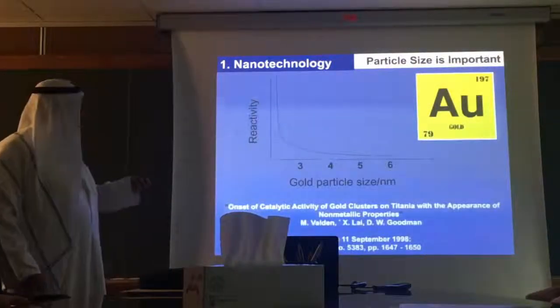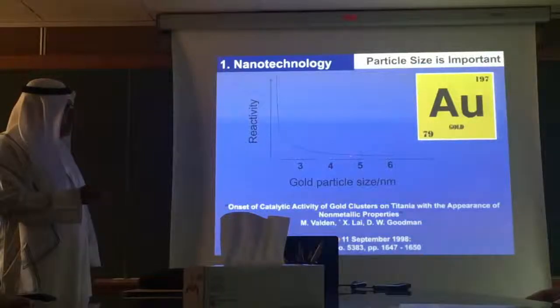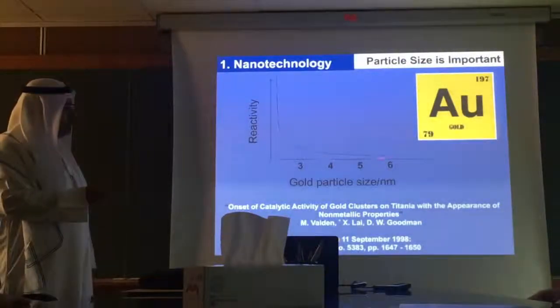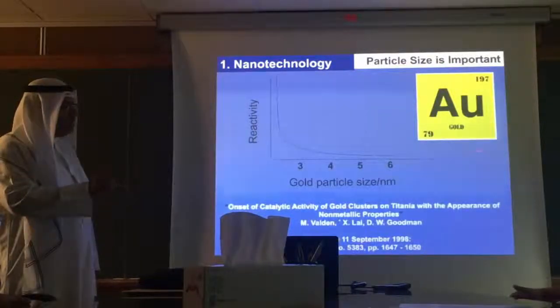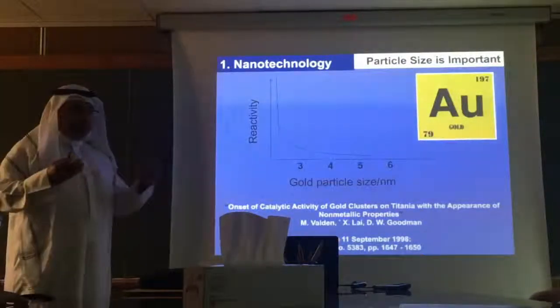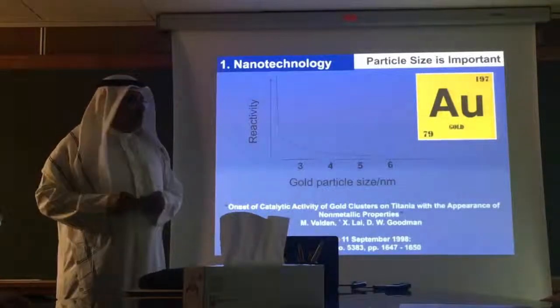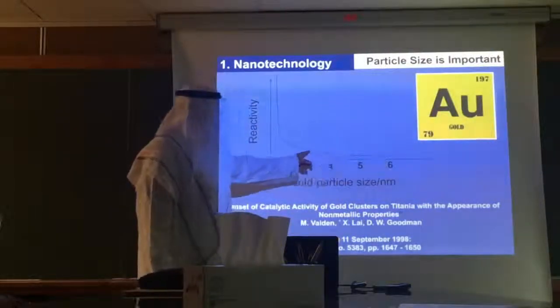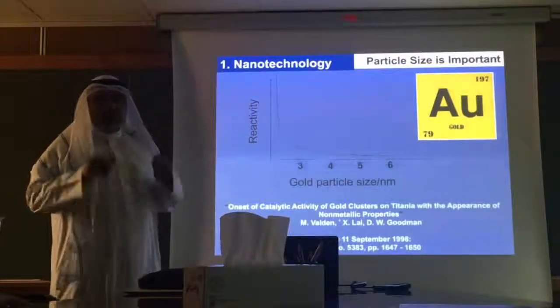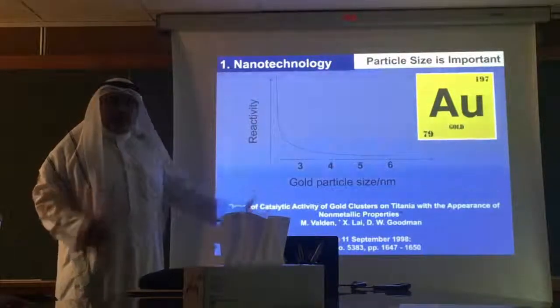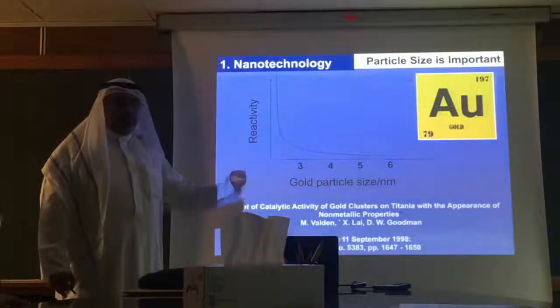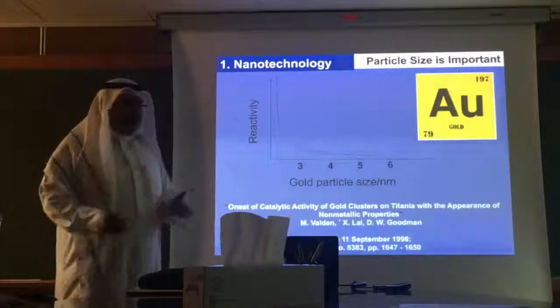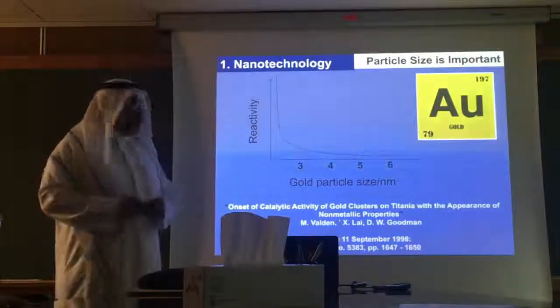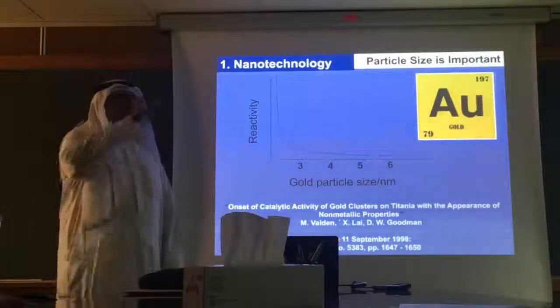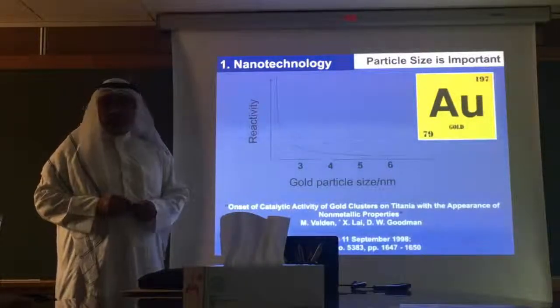This is a plot showing how gold becomes very reactive when the size starts to become smaller than 5 nanometers. Above 5 nanometers, there is not much of interest. It will be just normal gold. Expensive, it will not react with acid or base or any other material, so we can use it as jewelry. But below 5 nanometers, look how sharply the reactivity is increasing. Very, very sharply. They use it as a catalyst. Gold, which we call inert, will not react with anything, even strong acid. But when you make it small, it will be very reactive, and it will even interact with visible light.